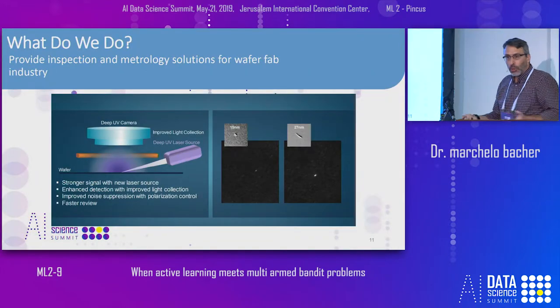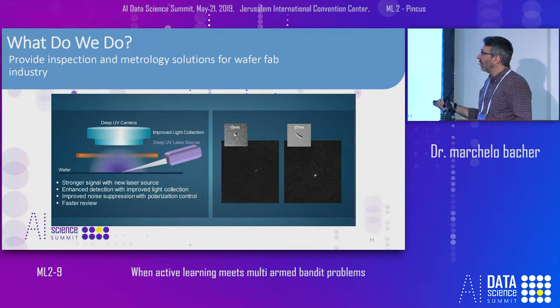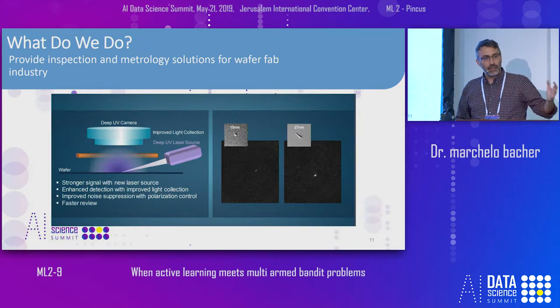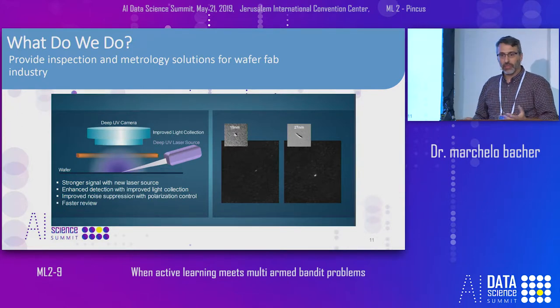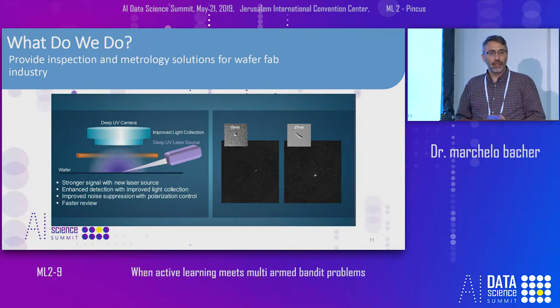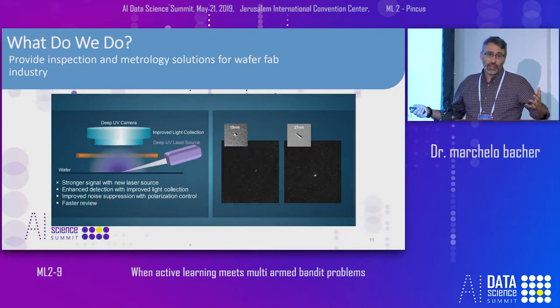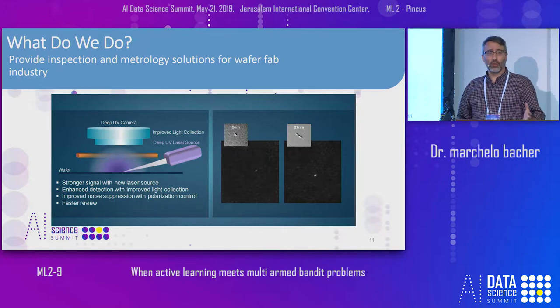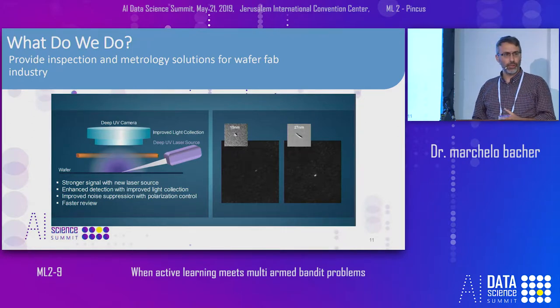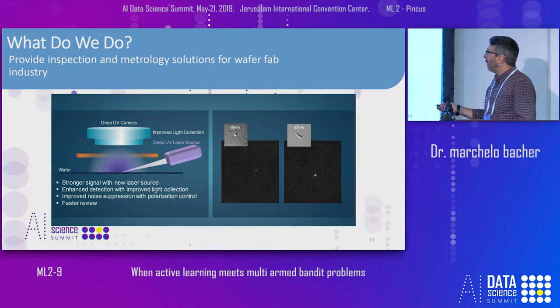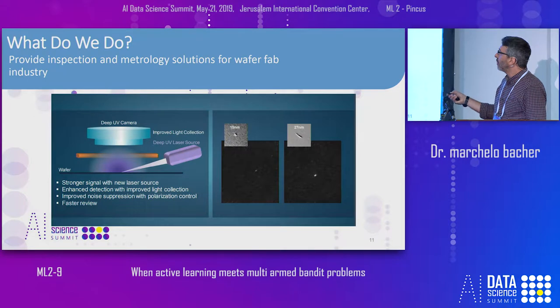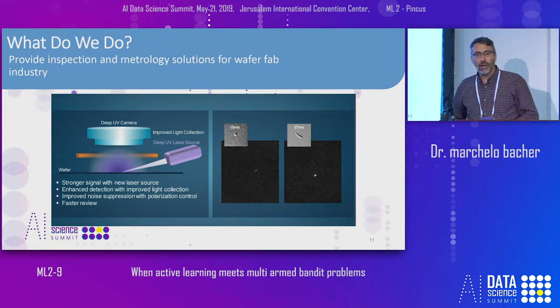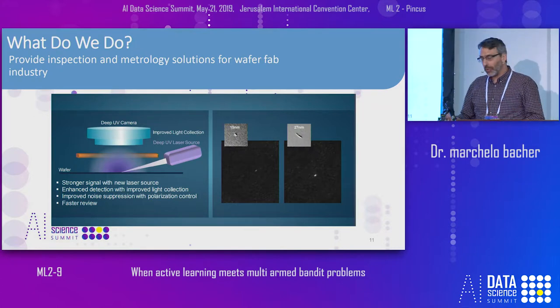So how do we do that? One of the equipments we develop here is an optical microscope that scans the whole wafer in around 10 minutes, generating millions of pictures. It's a microscope that is not quite small — it's usually fixed in a nine square meter room and connected to a supercomputer where all the magic happens. In that case you can find a 50 nanometer defect or a scratch of 20 nanometers. And those pictures that we see here — they look very nice. Normally, that's not the case, for reasons we will see now.